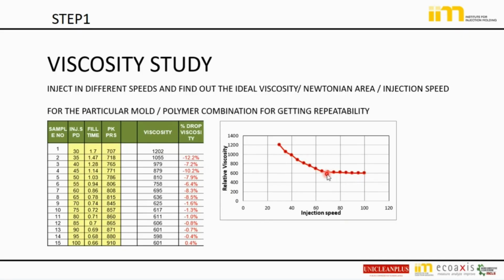We identify, for my material, what speed is best for injecting that part with that mold, with that raw material, and that machine. This is what we have to identify, and with this speed we'll go ahead. Of course, when the speed is higher, there may be some air entrapment and shear marks in the gate; that you have to handle with tooling knowledge. Shear rate calculation and air venting are the principles, and if you are able to do that, then you will get fantastic viscosity and consistency.